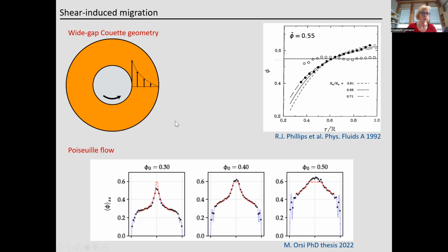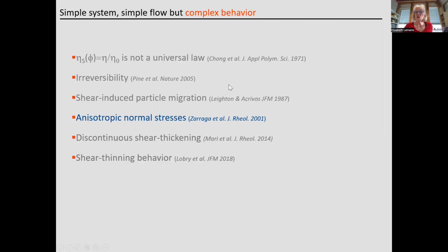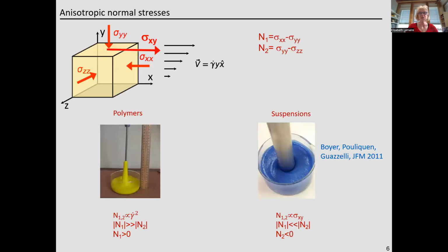And it's also what you can observe in a Poiseuille flow. So here I have put some results from the PhD of Michel. See? So in a Poiseuille flow, the shear rate is lower at the center than near the walls, and the particles tend to migrate toward the center of the channel. Okay, with non-Brownian suspensions, we have also many non-Newtonian effects. In particular, we have anisotropic normal stresses.